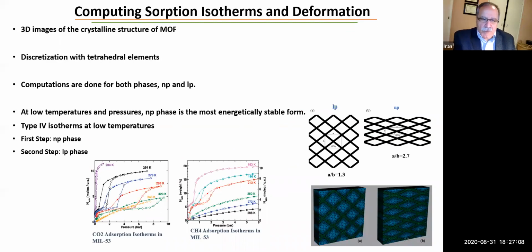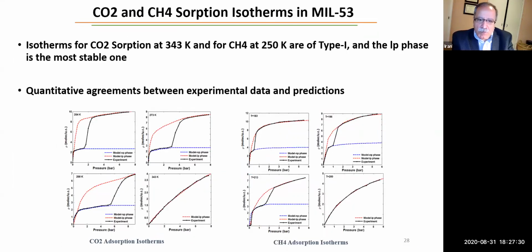There are all sorts of data. The typical experimental data is shown at the bottom. The structure that we simulated is on the right, with different aspect ratios. One is a large pore and one is a narrow pore. They have different aspect ratios, and therefore they simulate the structure. We discretize the structure and solve the governing equation that I showed you, and we get this. This is exactly what you see in experiment: a narrow pore at low pressure, and then a large pore at high pressure.